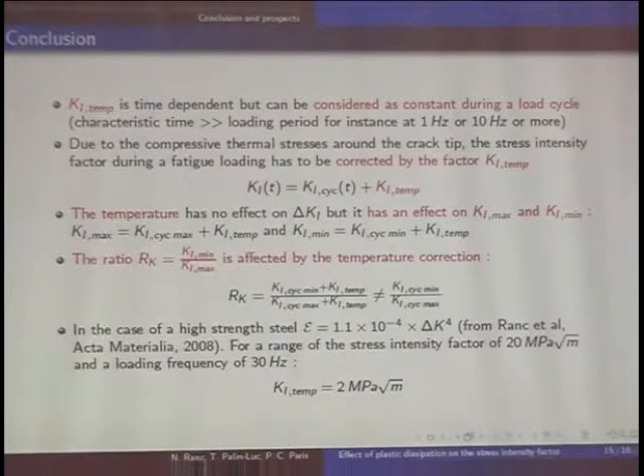So, of course, the key point is what is the effect quantitatively, because now we have solved analytically the problem. If we consider a high-strength steel, Nicolas Rank has shown that the energy dissipated per cycle, here it's per loading cycle, is around 10 to the power -4 multiplied by delta K power 4. And this is for a high-strength steel. If you include this value, for instance, when the stress intensity factor range is 20 megapascal square root meter at 30 Hz, don't forget that all the results are proportional to the loading frequency. In this case, the effect on the stress intensity factor due to temperature is around 2 megapascal square root meter, approximately a factor 10.